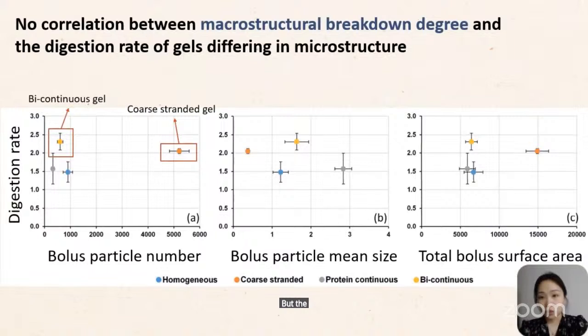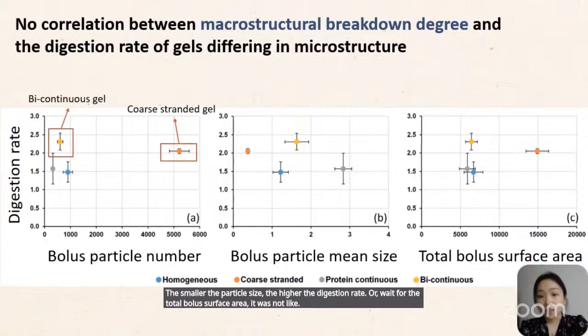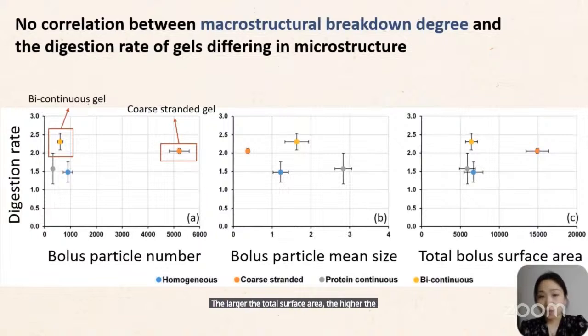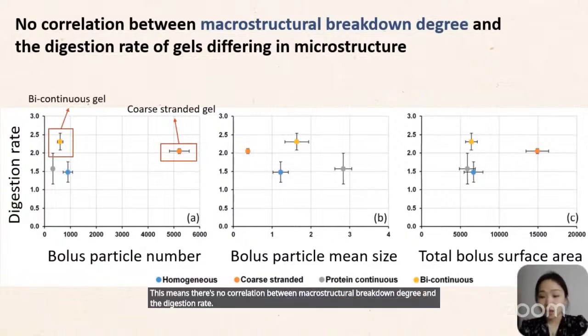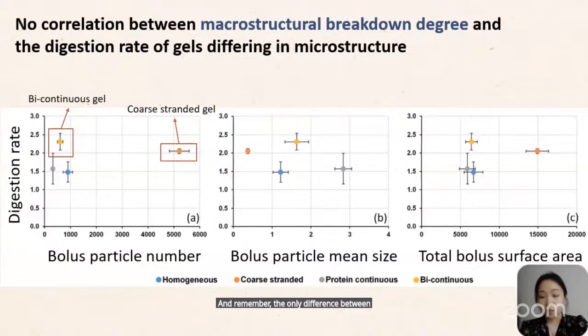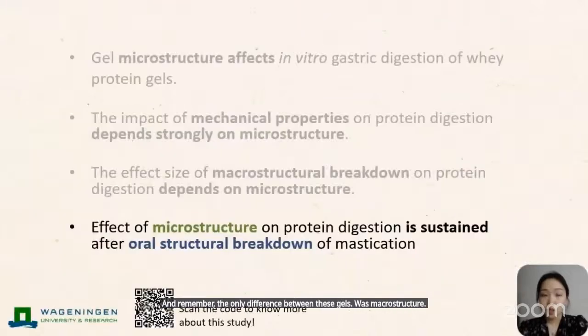But the coarse-stranded gels still show a lower digestion rate than the bicontinuous gels. And for bolus particle mean size, we did not find that the smaller the particle size, the higher the digestion rate. Or for the total bolus surface area, it was not like the larger the total surface area, the higher the digestion rate. This means there is no correlation between macrostructural breakdown degree and the digestion rate. And remember, the only difference between these gels was microstructure. So we concluded that the effect of microstructure on protein digestion is sustained even after oral structural breakdown of mastication.